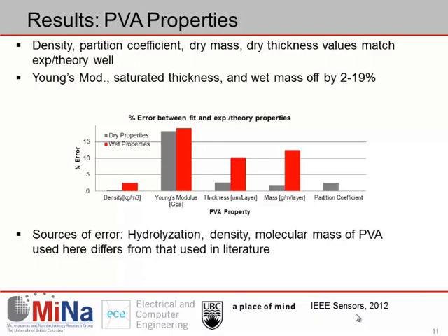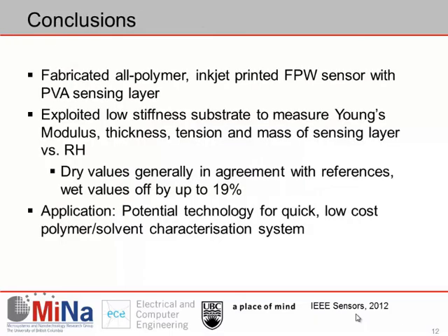Another factor which isn't accounted for here is a confirmation of how tension is shifting. While we did measure tension, we were unable to confirm exactly how tension was changing in the thin layer. So this could be contributing as well. So to summarize, we fabricated an all-polymer inkjet printed flexural plate wave sensor with a PVA sensing layer. We exploited the low stiffness substrate to measure Young's modulus, thickness, tension, and mass of the sensing layer as a function of RH. And then we compared a number of these values, finding that they agreed generally in the case of dry sensing, but in wet sensing they were off by 19%.